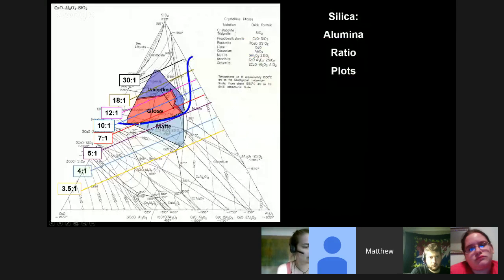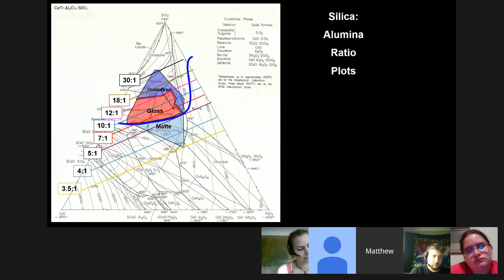Here's the formula for anorthite: one calcium, one alumina, two silica. So it is this excess alumina that generally forces the crystallization in the upper region. And again, this is where it starts to get tricky, and what yesterday's lecture was really talking about is that we actually have multiple forms of crystallization dependent on the material.